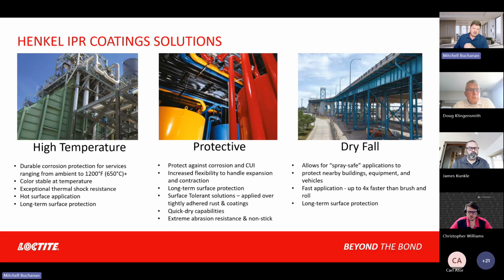And then, so kind of cover this, but one of the big things, right? So high temperature, 1200 Fahrenheit, you're going to need protection. CUI is a major concern here. The corrosion sweet spot, right? You hear 120 to 320 Fahrenheit for corrosion under insulation. That's when you're getting rapidly accelerated rates of corrosion.